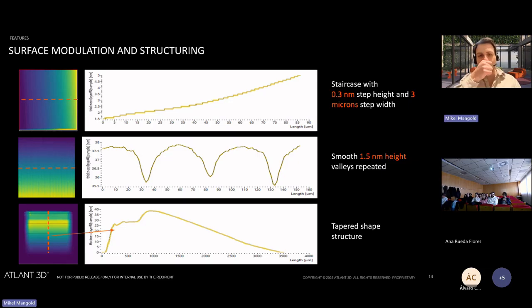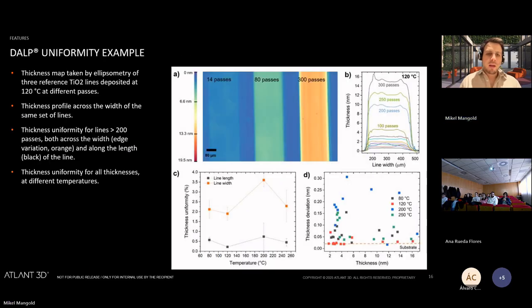The great thing with our tool is that we can control stoichiometry, we can control the pattern, but we can also fully control the thickness. Because we can fully control the thickness, we can create almost perfect gradients, like 5 nanometers at a time, or we can even create valleys of material as you can see. So we can completely control that. Now, how do we control that? It's like a pen that we bring to the surface. We just need to come multiple times with the pen, and then you do many passes.